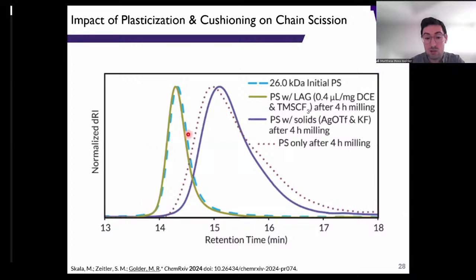So we see no change in molar mass here at all, which is good, right? We're not getting mechanochemical chain scission to any appreciable degree. If we mill with just the solids, or if we just mill the polystyrene, we see a shift to longer retention time, which implies that we're starting to mechanochemically cleave the backbone, and we see an increase in dispersity as well. Right, so this was really good evidence that liquid-assisted grinding could potentially quell this reaction.